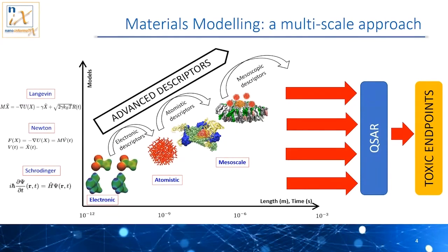The calculation of descriptors is generally quite expensive in terms of computing time, so it is harder to generate a large dataset. Moreover, the quantities are very specific to the input structure. For example, they depend on the size and also on the shape of the nanoparticle simulated, its crystalline or amorphous structure, and the results are sometimes hard to compare with the experimental ones because the computational conditions are somewhat perfect. For example, a perfectly spherical nanoparticle in pure water, whereas the experimental conditions are more complex.